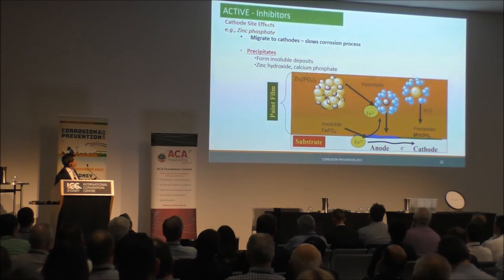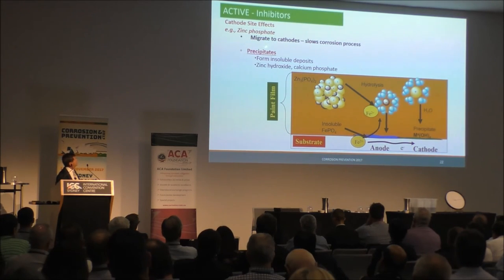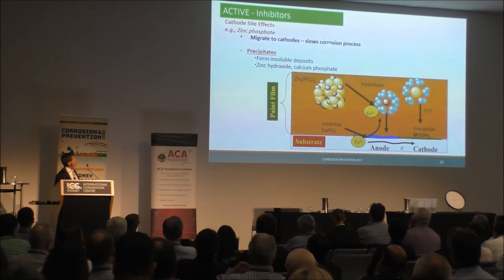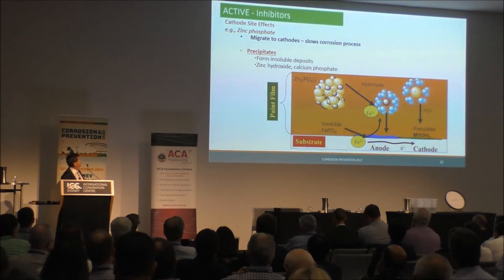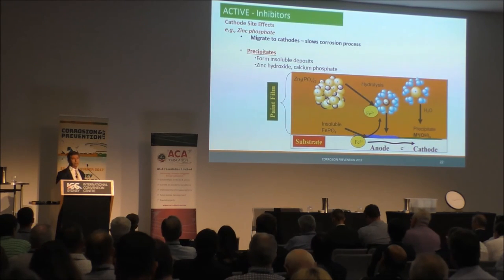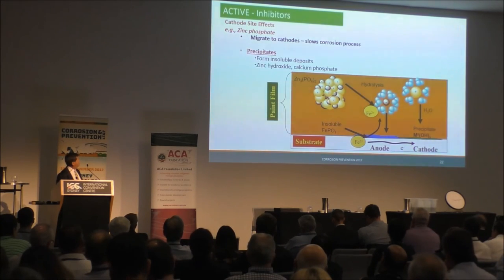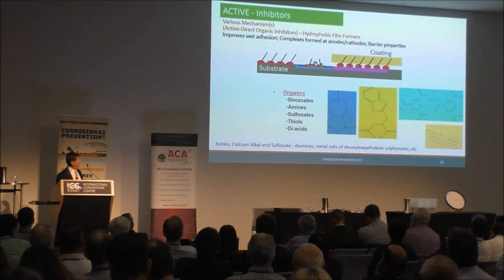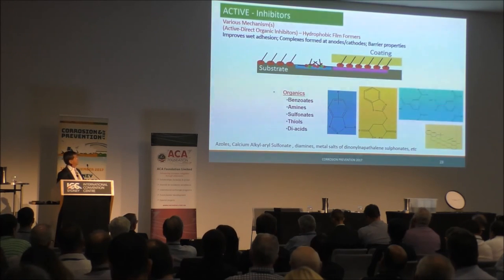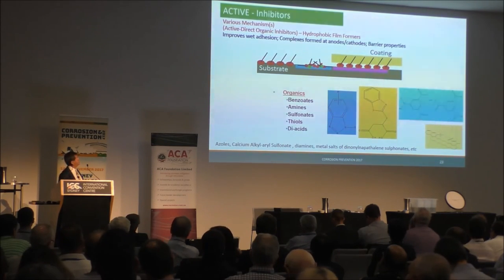But there's other types of active inhibitors too that really function primarily at cathodic reaction sites, like zinc phosphate is a good example, where here the material migrates to the cathodes under the water transport front, and it simply slows the corrosion process down at cathodic sites. So essentially here, with these kinds of inhibitors, we're really producing corrosion products at cathodic sites primarily, which are simply more insoluble than the products that would form if you didn't have the inhibitors there. So, it gives us lots of opportunities to design a coating to have different characteristics, all of which are aimed at providing good performance and corrosion resistance.